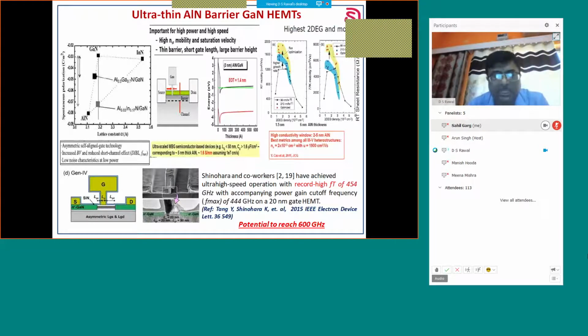On the first day, there was a question: are these devices suitable for terahertz applications? Yes, people are exploring these devices, and this is one device having a gate length of the order of 20 nanometer, and the cutoff frequency reported for this device is 454 gigahertz. People are exploring these kinds of devices up to 0.3 to 0.4 terahertz for imaging applications. These devices certainly have potential to go beyond that. But so far, the best reported FT of a device with 20 nanometer using an aluminium nitride/gallium nitride heterostructure is 454 gigahertz.